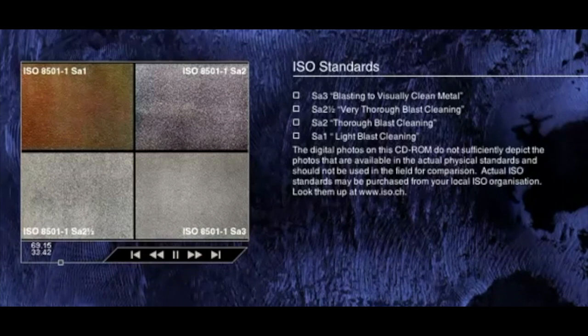Each system of standards represents a progressive scale of visual appearance only, the best grade being shown first in each case. The quality of blast cleaning is determined visually, and photographic standards are generally used for comparison purposes. There is no correlation between the degree of blast cleaning used and the surface profile produced, and no specific correlation with removal of chemical contamination or non-visible salts. For these issues, other standards and measuring techniques must be used.